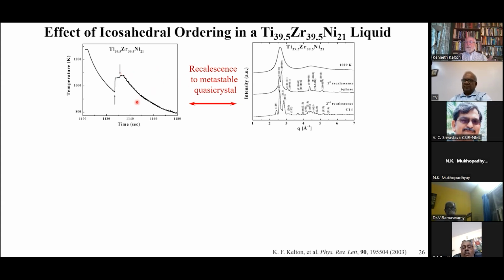Because we were using such high intensity X-rays, we were able to trigger on the first recalescence. And even though this plateau is only 2 or 3 seconds long, we could get a complete diffraction pattern. And what we found was that this first recalescence was to an icosahedral phase. The second recalescence was to the equilibrium phase that we expected, which was a C14 Laves phase, a complicated intermetallic.